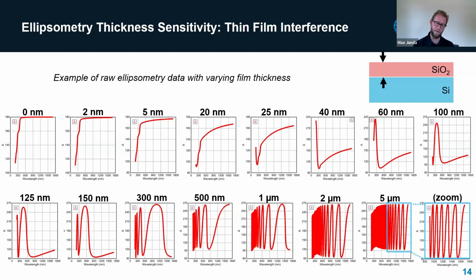And you can see, particularly on the left side at the short wavelengths in all of these spectra, the emergence of these oscillations in the data, basically wiggles. And so you can see as we add more and more thickness, these wiggles are starting to pile up. And then we go through 150, 300, 500, 1 micron, 2 micron, and these wiggles start bunching together. And so effectively, you can get an intuitive understanding here that if we're able to fit this data and then fit how tightly bunched in the spectrum these wiggles are, we're getting information about how thick this film is. And you can see I've even zoomed in on the right for 5 microns. It can get really tight, and that starts to get into what gets tricky about measuring very thick films, which we will cover in a second.